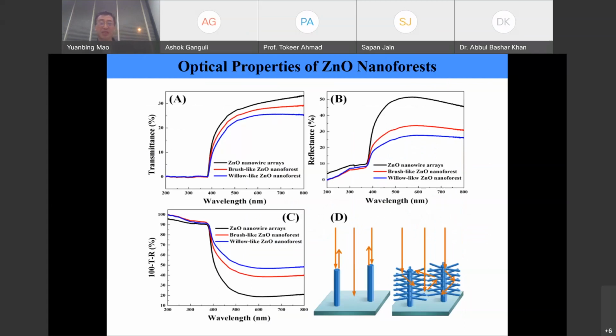So what we did is we use UV-vis, and we can really confirm that. The first thing is we can just take the transmittance. Then you will see here that the willow-like zinc oxide nanoforest gave the lowest transmittance, and the zinc oxide nanowire arrays give the highest transmittance. That means more light goes through the sample. And then we can take the reflectance, and you will see that the zinc oxide nanowire arrays give the highest reflectance.